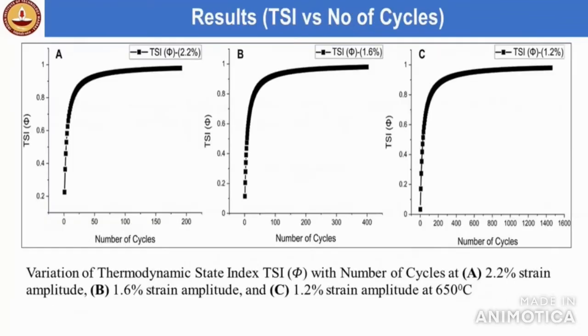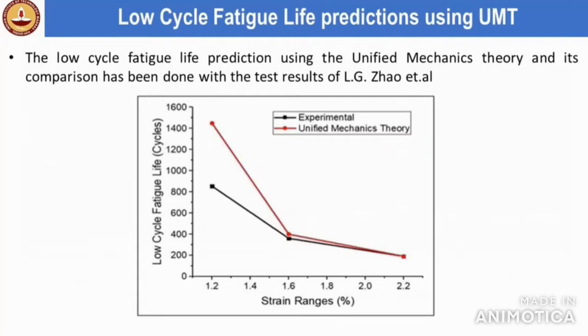In the ongoing work, we developed an analytical model to predict low cycle fatigue life, which uses plastic dissipation as the primary source of dissipation. The results of thermodynamic state index versus number of cycles can be seen in this figure. Using an analytical model based on unified mechanics theory, we calculated fatigue life. This matches well at low strain amplitude, and at high strain amplitude there is a slight deviation, as we can see in this figure. This is because the boundary or the geometrical effects are not considered in the analytical prediction.